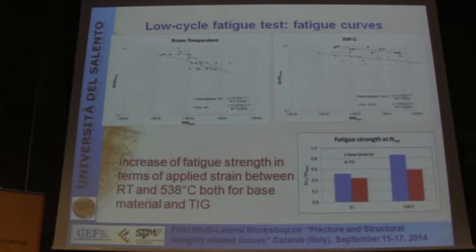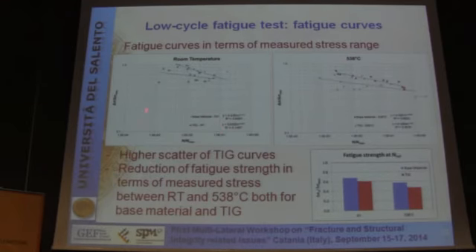Finally, the last result of the fatigue test was the fatigue curves, which we can express in terms of applied strain range, like in this case. And here we observe a reduction of the fatigue strength, which is very high at the working condition. The same curves can be expressed in terms of the measured stress range, and in this case, the reduction is more limited in the hot condition, but we observe a high scatter here and here, both at room temperature and in working condition.